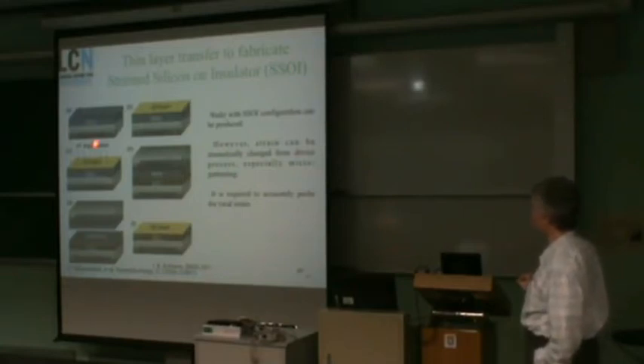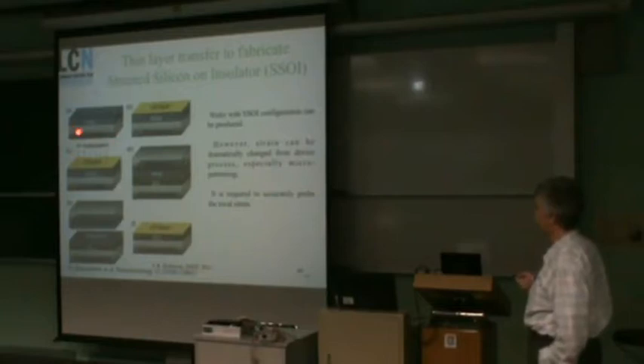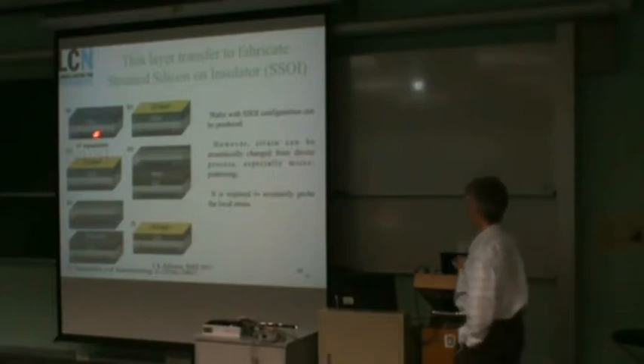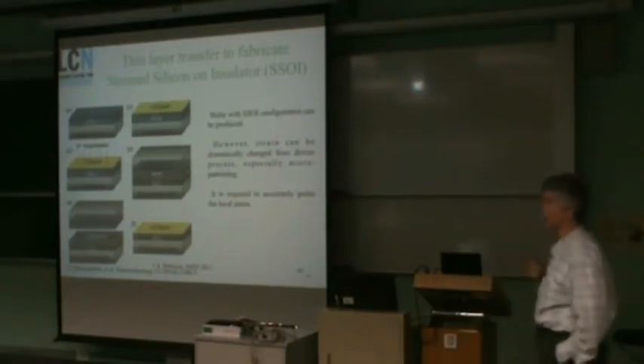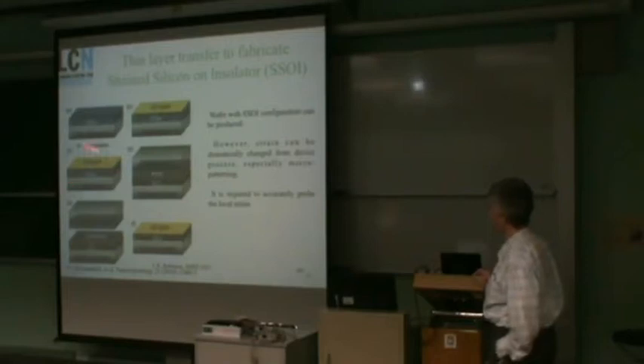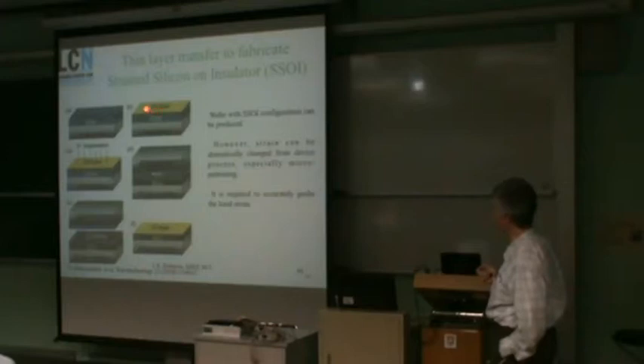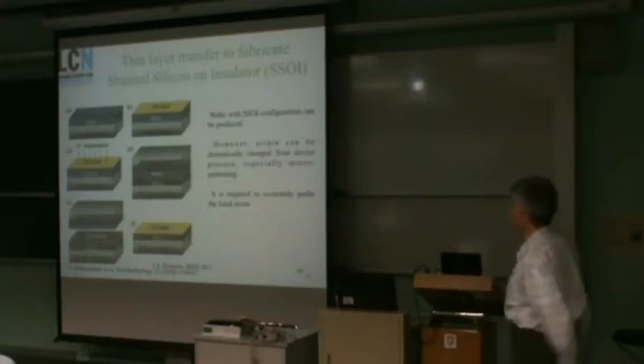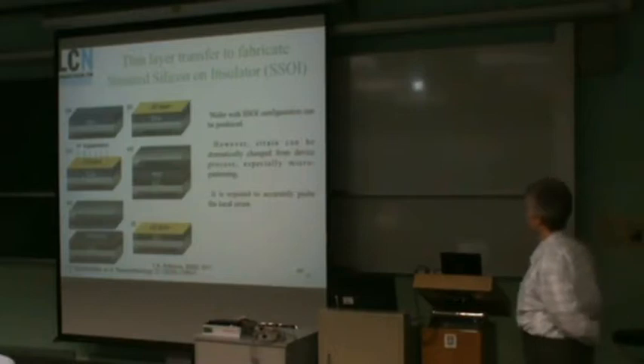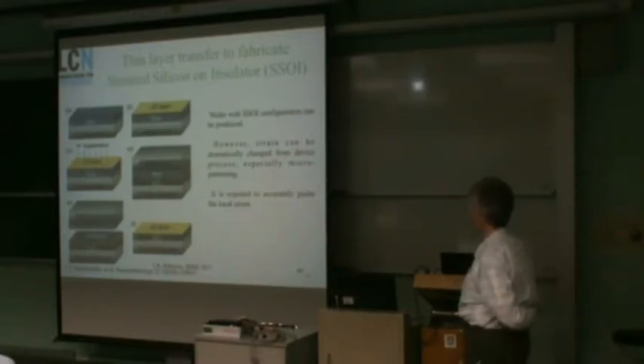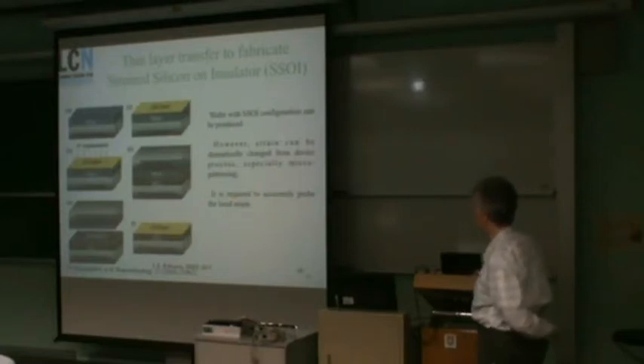And what's done here is that you start with a silicon wafer. You grow a sacrificial layer of silicon germanium with defects in it, which is then thick enough that it's fully relaxed to the silicon germanium lattice constant, which is larger than silicon. And then when you grow an epitaxial layer of silicon on top of it, shown here, then you get the tensile strain in the silicon layer that is desirable for the improved mobility of the silicon in that layer.